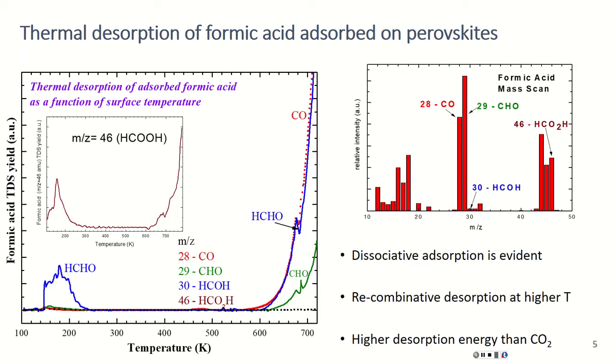At the same time, we can detect only 4 fragments with proper intensities. So if we want to do both, then we have the dissociation fragments of formic acid, but if we want to detect the desorption fragments of the perovskite layer, we need to do a different experiment. So we can simply synthesize the perovskite layer and adsorb a formic acid layer like this, and then we can try to desorb it. We can just do the thermal ramp, detect those dissociation fragments of formic acid, and see at which temperature those fragments are desorbing.